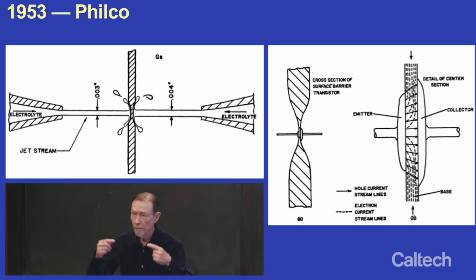had a little spout on both sides, and they would squirt electrolyte on the germanium. And if you put a current into the electrolyte in one direction, it would etch away the germanium, and if you put the current in the opposite direction, it would deposit indium. So this was an automated way to make these PNP transistors.